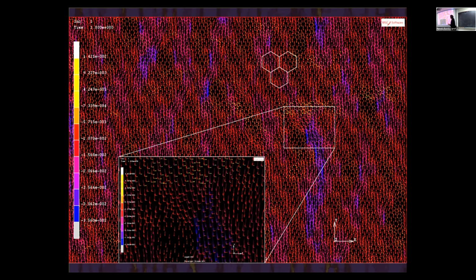Another interesting observation here is the size of a couple of grains. Now what I'm doing is, at each node, I'm plotting the components of the stress tensor. In yellow we have tension, and you can see the little arrows pointing out this way. So even though we're compressing this thing, we have regions that are slightly in tension. We have a huge variation in the compressive stress. The blue is the highest compression here, and again, you can pick up that pattern.